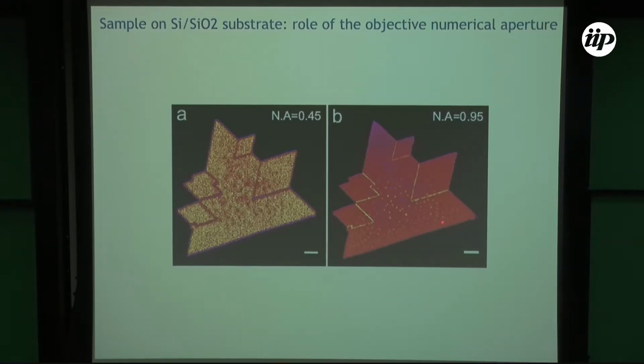The difference here is that because of the silicon substrate, we believe there are some reflections coming from the silicon substrate. So the problem is much more difficult because you need to consider this type of reflection. When you use a high numerical aperture, you collect all of this light that is being reflected from the silicon, and then you can observe the grain boundaries. This is even without doing the dark field part. This is just bright field.